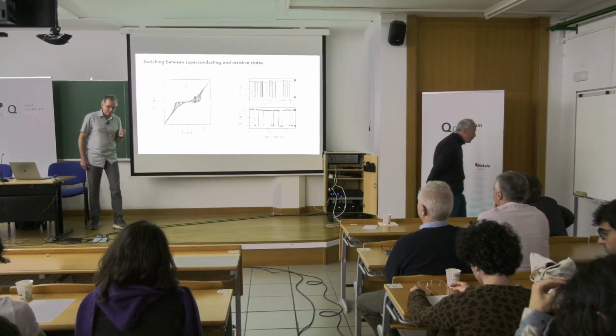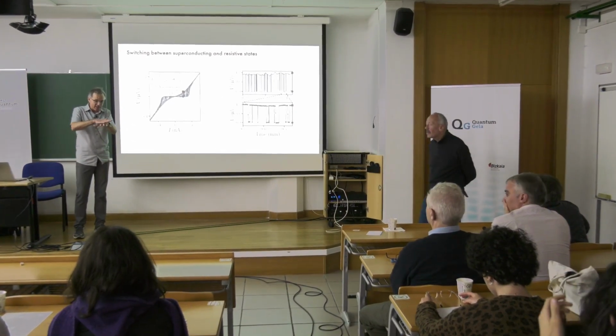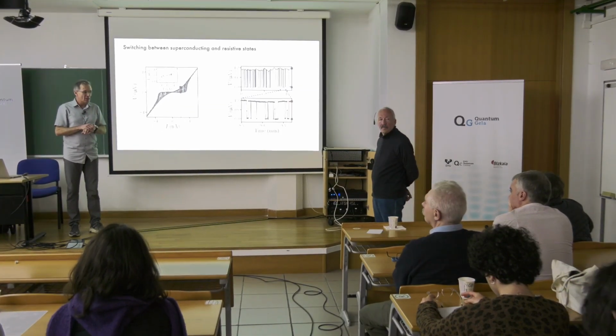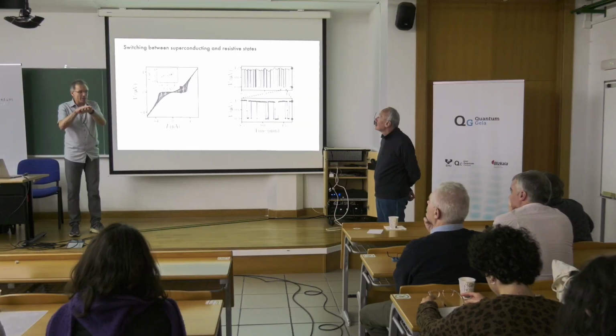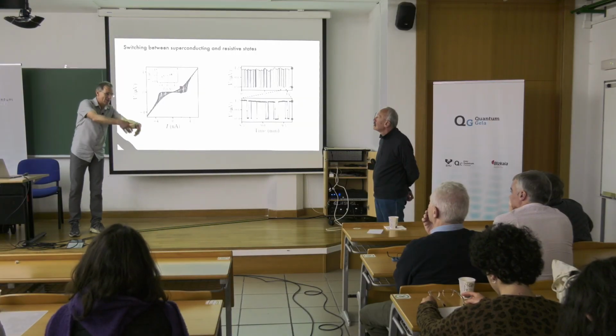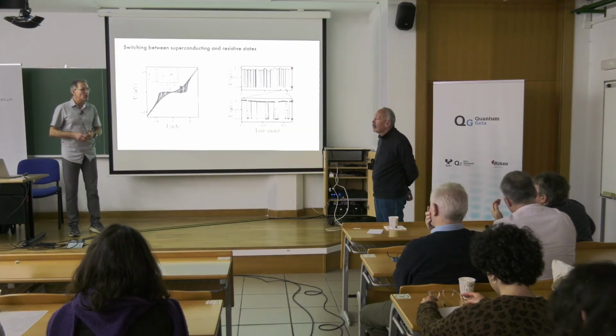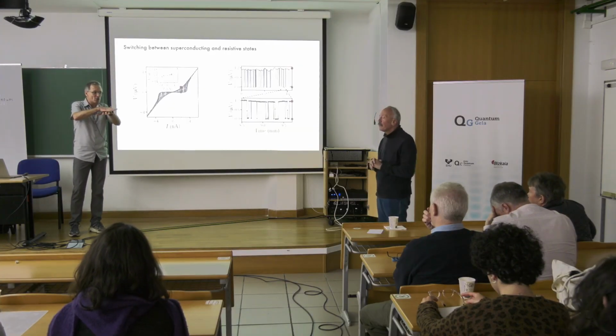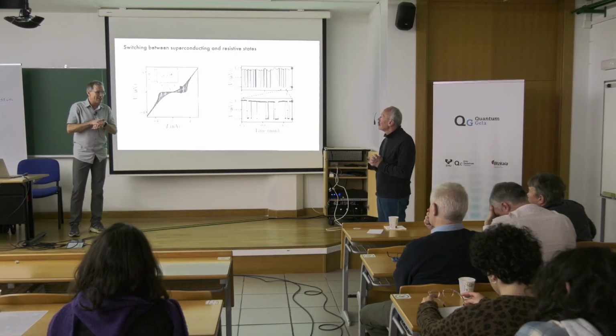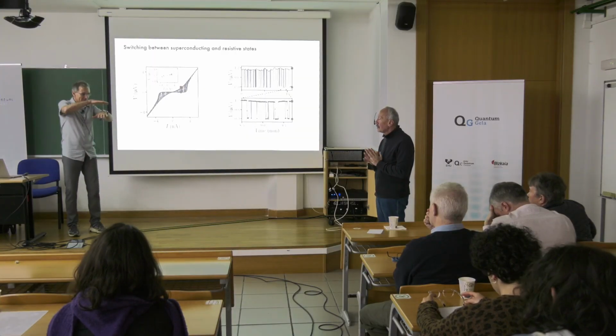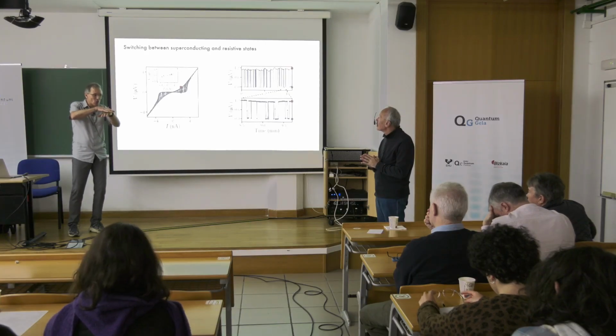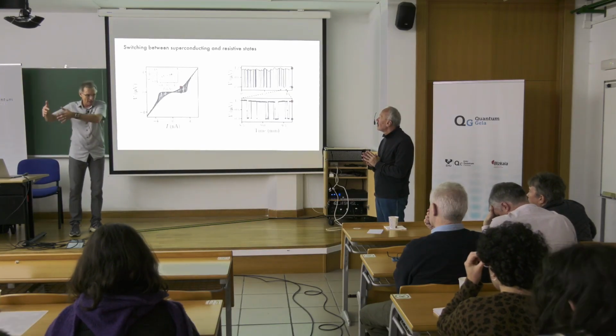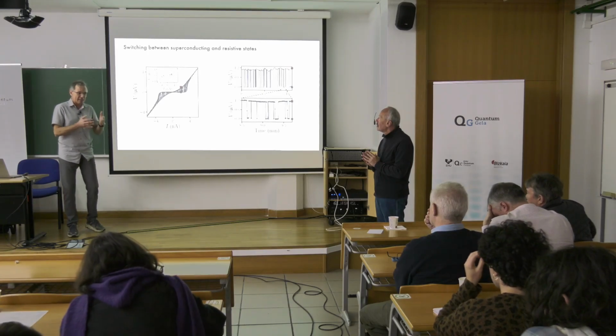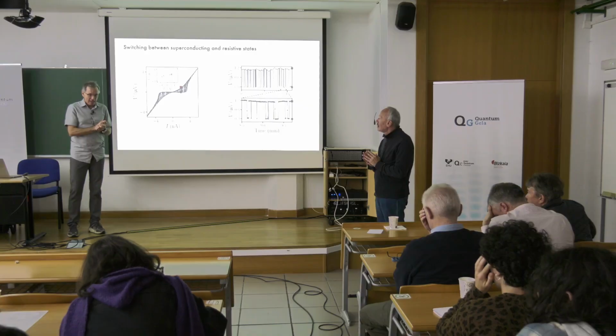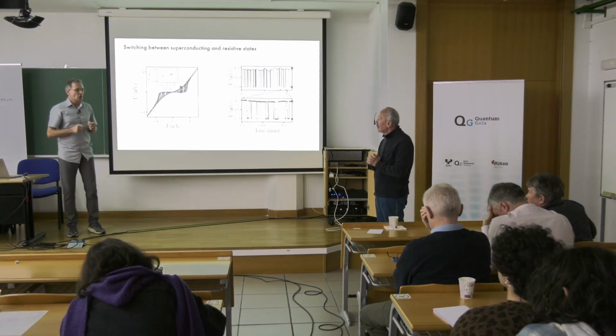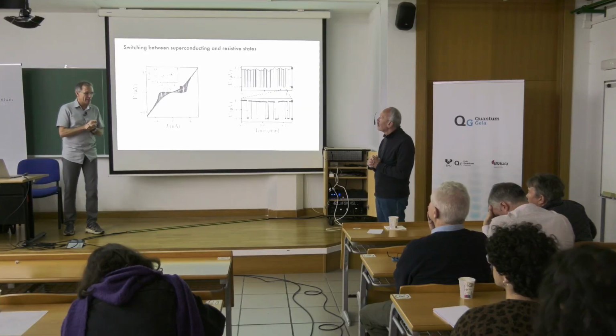So, as I mentioned, this magic angle twist was first predicted theoretically by calculating the band structure and so on, that there's this special angle of 1.1 degrees. And a few years after, people really produced this twist which was predicted and discovered what was predicted. So in this sense, you are right. But not everything one can predict.